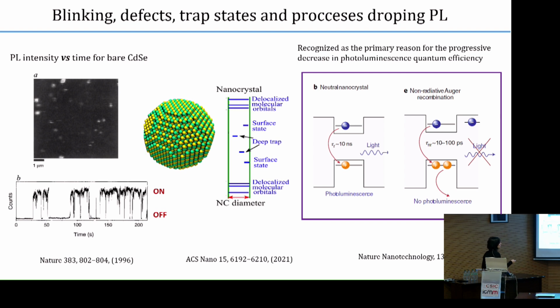One of the most important ones is the non-radiative Auger recombination, in which, without going into details, it includes the formation of bi-excitons, so two electron-hole pairs, and an energy transfer to a third carrier. I only mention this because this process is nowadays a bottleneck to use these nanocrystals in devices, where they are electrically excited instead of optically excited. And I will come back to this later. In the Auger process, there is later another extra process that thermalizes and gets the carrier back. So this is just one part, but there is also ionization, so there are several processes that go on.